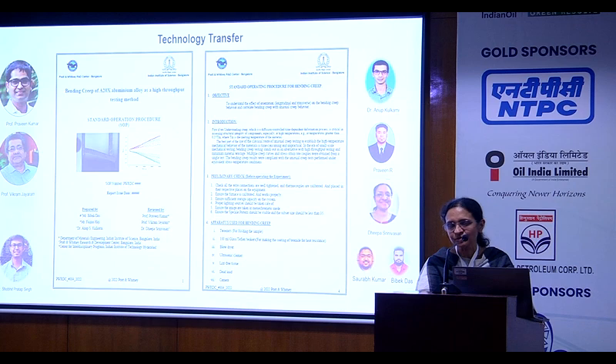development of high temperature materials, especially very, very high temperatures, nickel-based superalloys, cobalt-based alloys, and also looking at failures. For example, last year there was a big geared turbofan failure that was in all the papers, a Pratt & Whitney engine, and we were able to find the root cause of failures in a titanium compressor disc owing to microtexture using this method. So we're able to identify that. Very successful collaboration, with a lot of students who worked on it currently in our center.